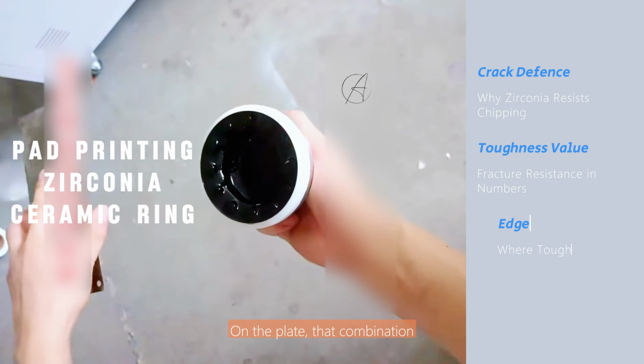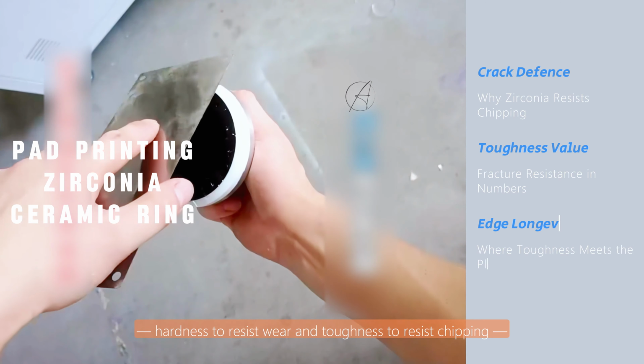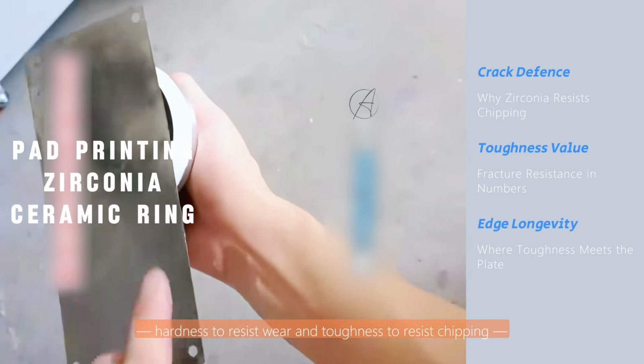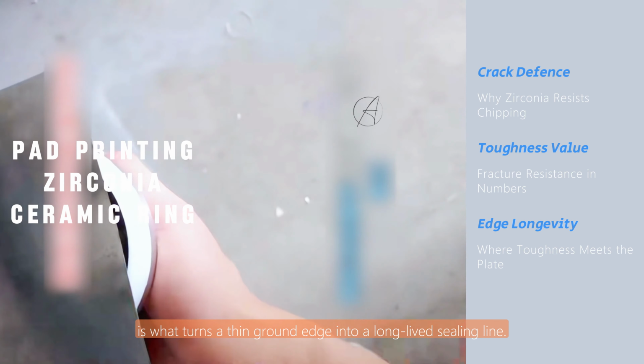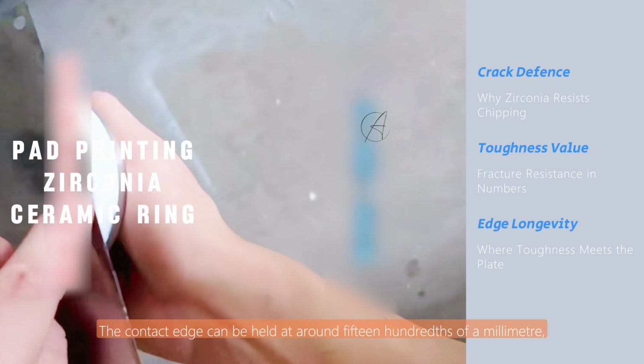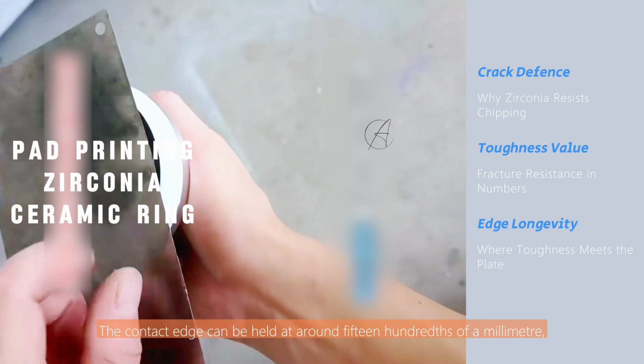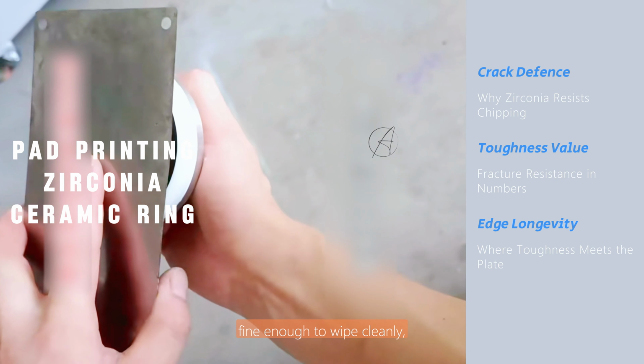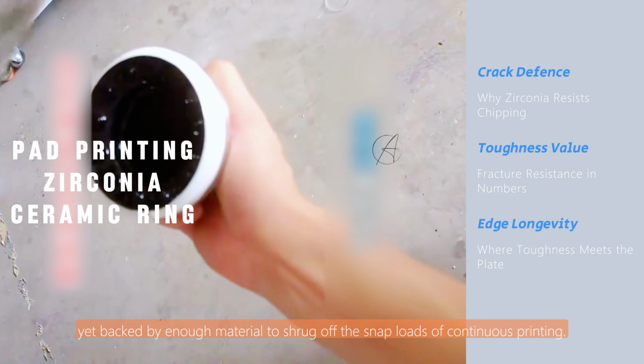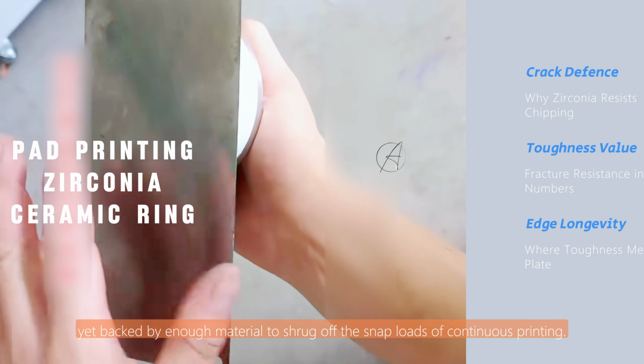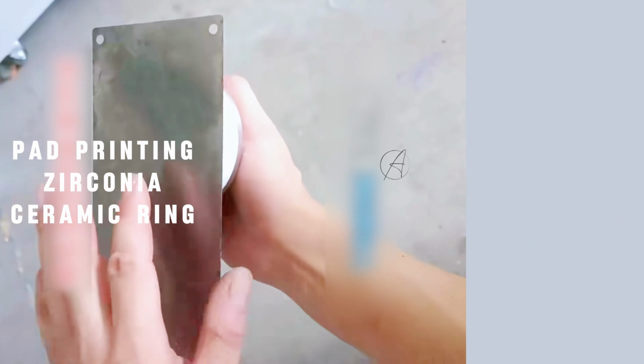On the plate, that combination, hardness to resist wear and toughness to resist chipping, is what turns a thin ground edge into a long-lived sealing line. The contact edge can be held at around 0.15 of a millimeter, fine enough to wipe cleanly, yet backed by enough material to shrug off the snap loads of continuous printing.